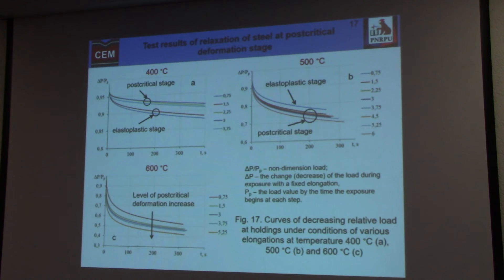Here you can see dependencies of non-dimensional load versus time of exposition for different stages of elastic plastic stage of deformation and post-critical stage of deformation. And you can see the intensity of relaxation of the load depends on level of post-critical deformation.